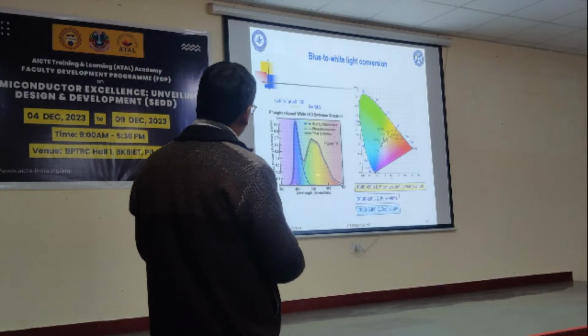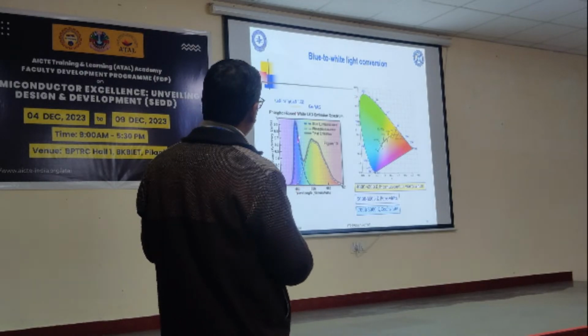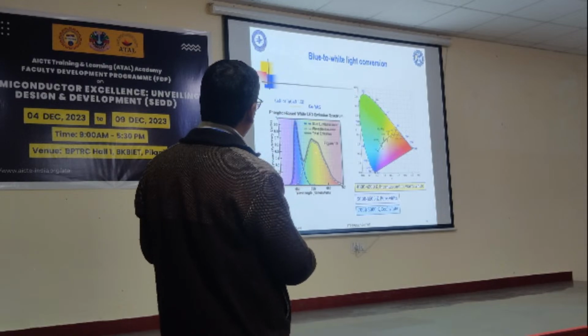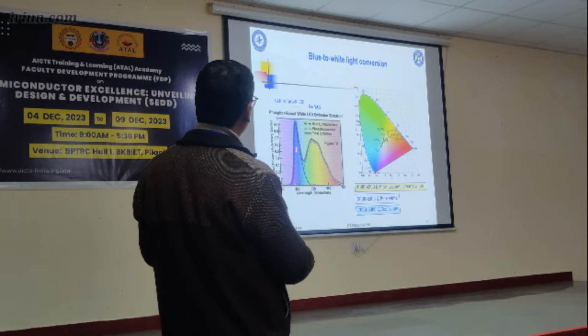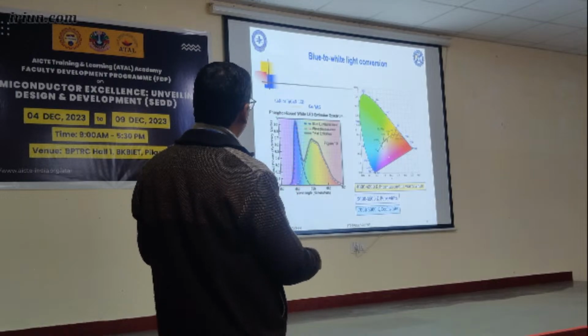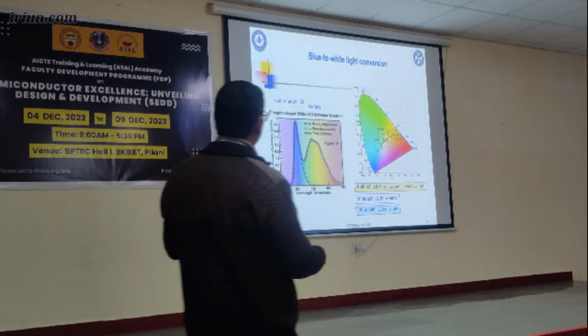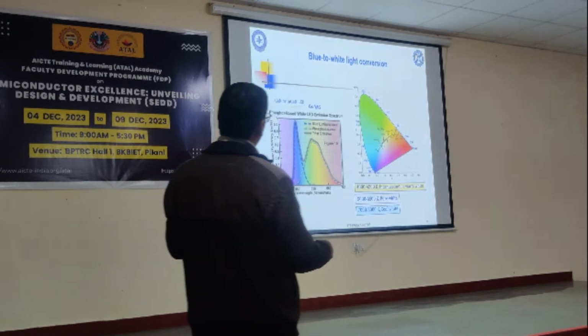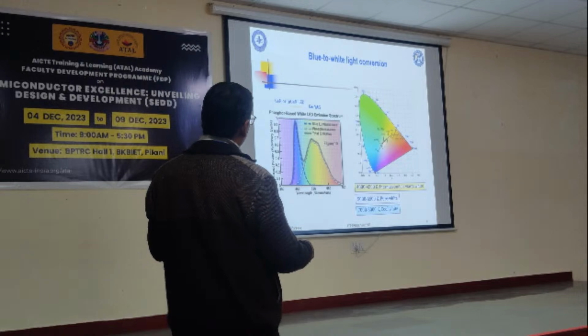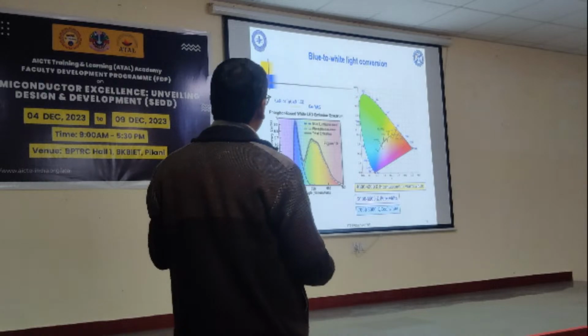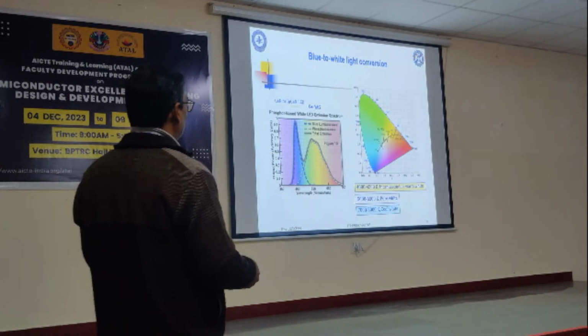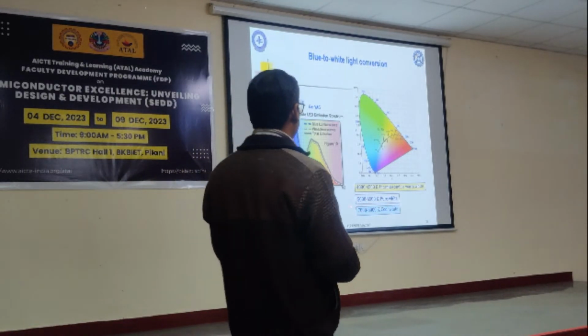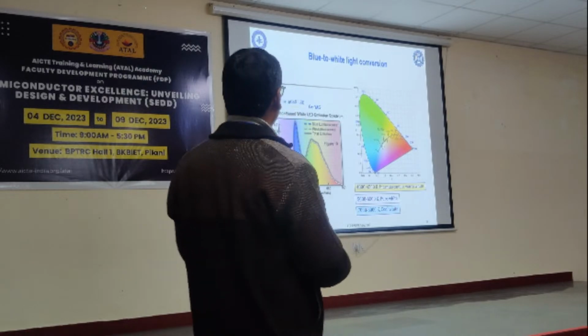So this is in general what we are getting in blue light, and this is the yellow phosphor combination. If we combine this yellow with blue, we'll get white. And in terms of color chromaticity, those will be the positions. So the white position will be here, and the color temperature for pure white should be around 5,000 to 6,500 Kelvin.